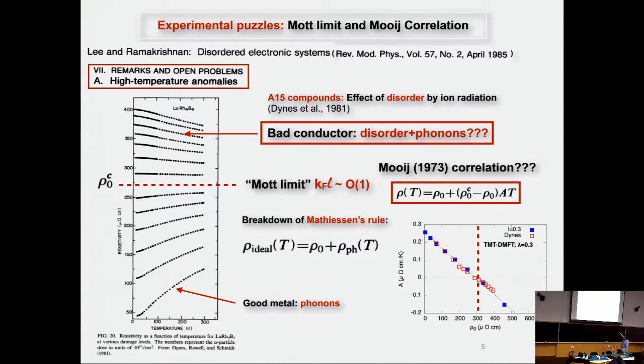It's shown here. Here is the prefactor, the linear coefficient, and here is the residual resistivity. You see that there is a linear behavior, and the red are the data from this paper, and the blue is the theory that I will describe in a minute. So this has been a long-standing puzzle. What is happening here, and is this something that you can relate to the approach of the transition, or something completely different? Is it related to Anderson localization? Is it related to something completely different?